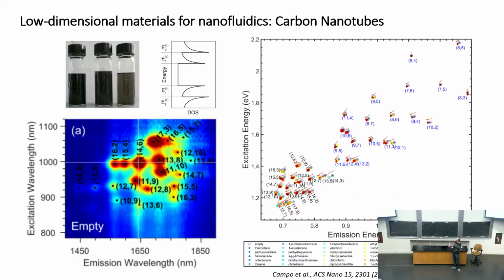Here's how people study it. I'm just showing that it took quite 10 years to figure out that when you make CNTs typically in powders in the beginning, you actually do have to separate them. You have to individualize them, because when they're in powders, you'll never be able to see any optical transition, which was believed to be a very good tool, between these Van Hove singularities in the density of states here, because you also have metallic tubes. As soon as they're in contact with metallic tubes, you quench any photoluminescence. So people first had to take powders, put them in solution, put surfactants in, sonicate to individualize them, and then they were able to do photoluminescence.